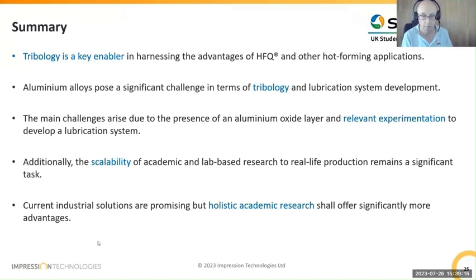The lubricants that we're typically using at the moment are graphite based, and the industry that we're selling into is not really used to using graphite based lubricants. So there's a lot of work going on to try and remove the graphite and replace it with other lubricant base, not just base fluids, but also additives to remove that solid lube. And whilst our current solutions are promising, we still need quite a bit of research to take place, not only within ITL, but also within academic research facilities, so that we can better realize the true advantages of this process.